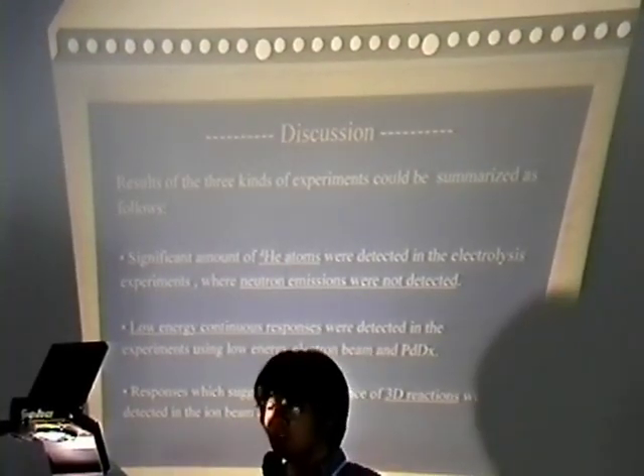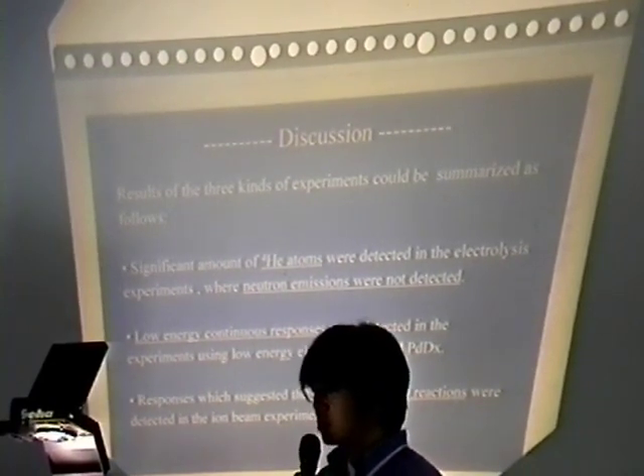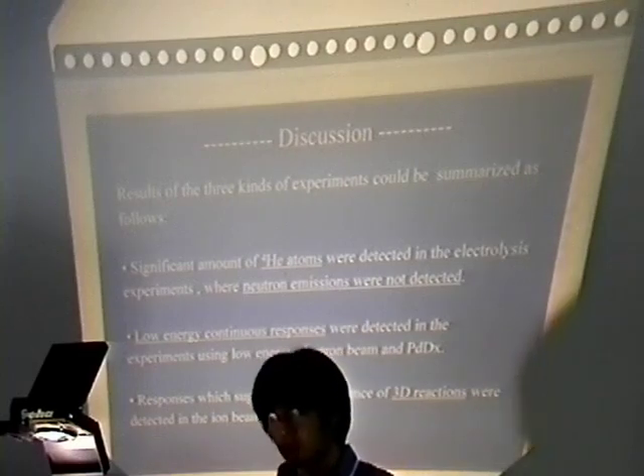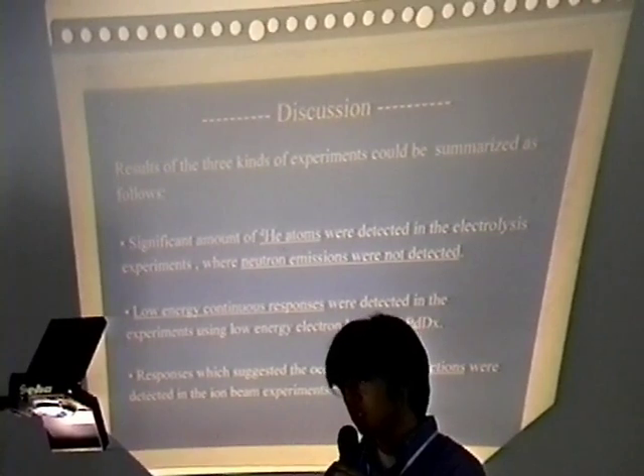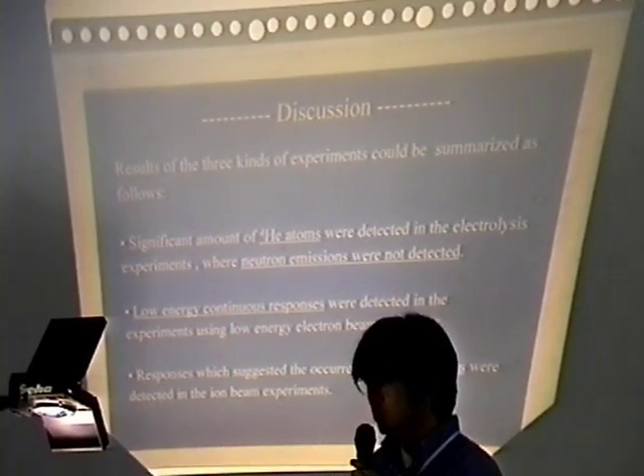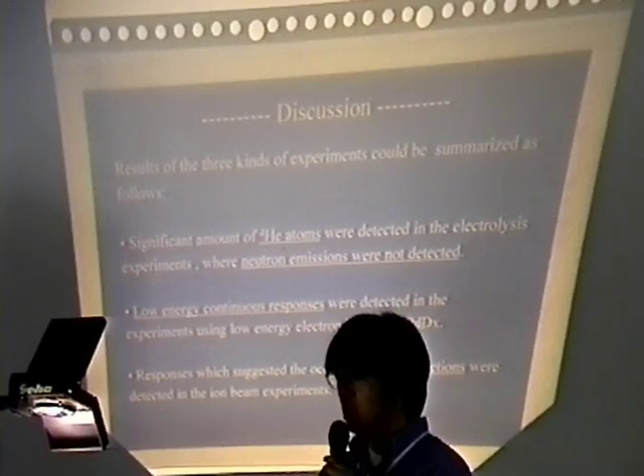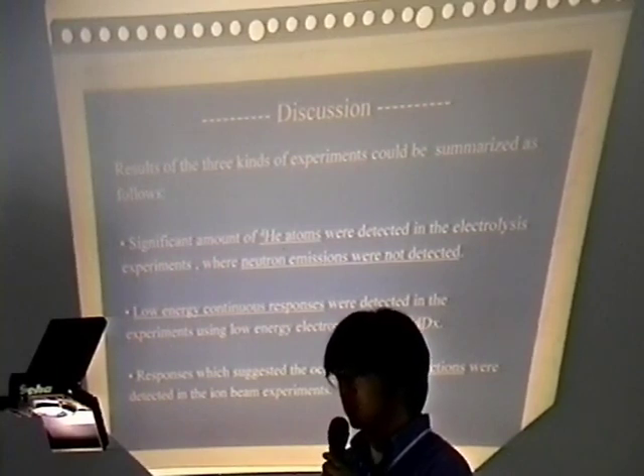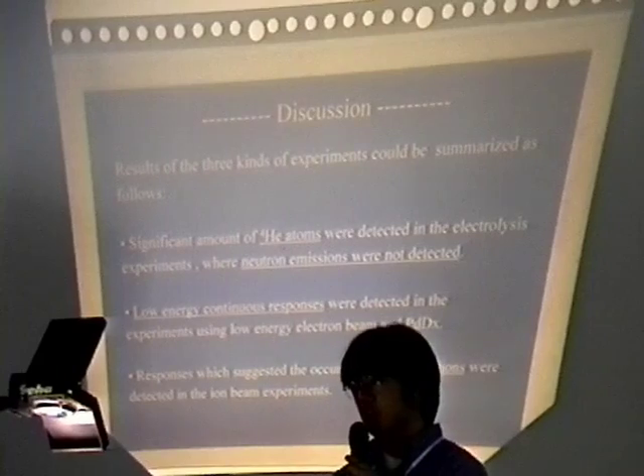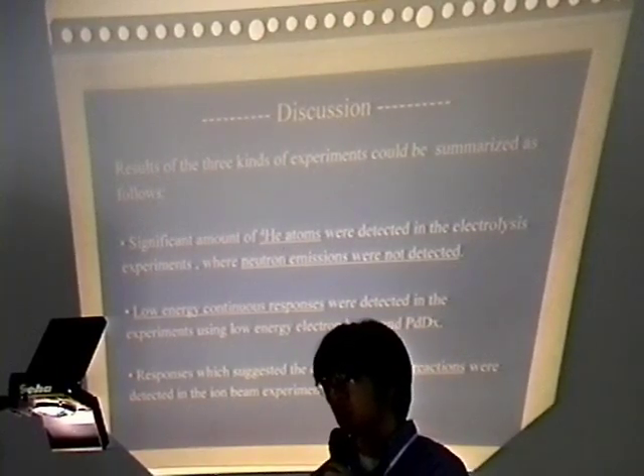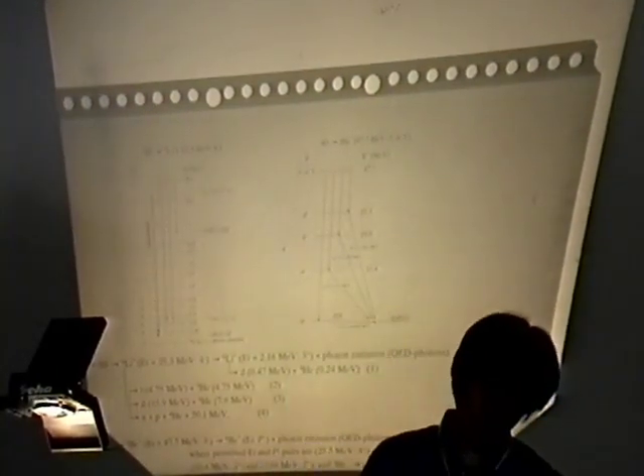At last, I make a discussion of these experimental results. The results of the three kinds of experiments could be summarized as follows. A significant amount of helium-4 atoms was detected in electrolysis experiments where neutron emissions were not detected. And low-energy continuous responses were detected in the experiments using low-energy electron beam and palladium deuteride. And the responses which suggested the occurrence of 3D reaction were detected in the ion beam experiments. So we conceive that multi-body reactions, 3D or 4D, are of key importance to explain the experimental results.